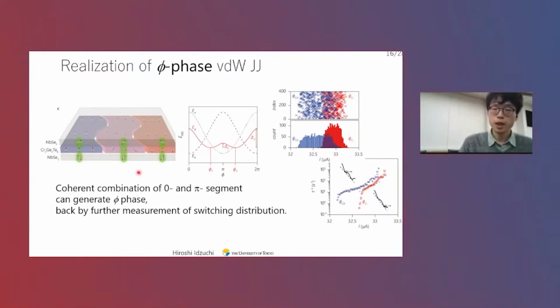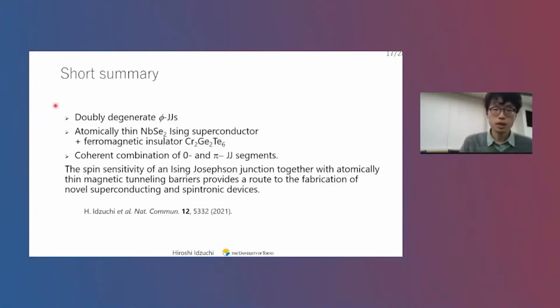And in experiment, we measure by sweeping many times, and then take the hysteresis, and then we can confirm whether this is consistent or not. So now we can have two different statistics of escaping from the potential well. So this indeed is consistent with what I explained. So in this part, I have shown the doubly degenerate phi Josephson junction. Phi means a non-zero, non-pi phase, some phase between them, and this is shown using atomically thin niobium diselenide and CGT, and explained by the coherent combination of zero and pi Josephson junction segments.